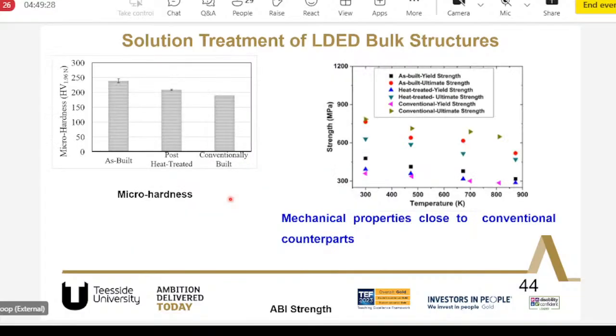So we did mechanical property evaluation from room temperature to high temperature, and we could compare it with the conventional material, and we could see that the mechanical properties are brought very close to conventional Hastelloy X, which is used for standard engineering applications.